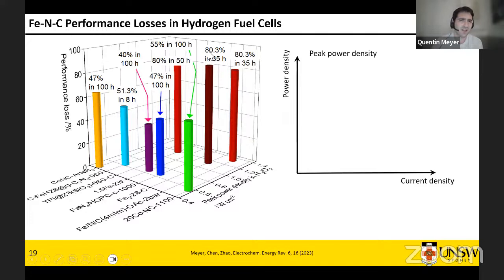So this one, 80% in 35 hours. This one, 51% in 8 hours. This one, 47% in 100 hours. This one, 40% in 100 hours. So overall, there's quite a sharp drop. And more worryingly, it's not just a sharp drop, it also happens at the beginning of life.